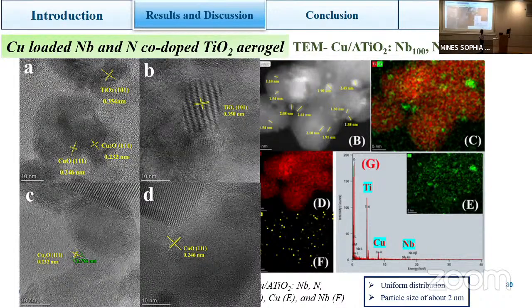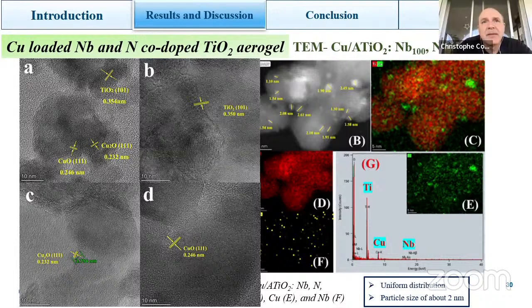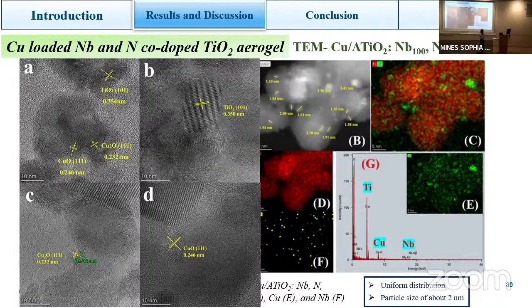Yes, it has to, because it's a solid-gas system, so the reaction occurs on the surface of the catalyst. It has to be adsorbed first, and the reaction happens on the surface, and then it desorbs. Yeah, but on the metal surface, not on the titanium dioxide. Yes, some of it happens on the particle, not a metal particle, a metal oxide particle.